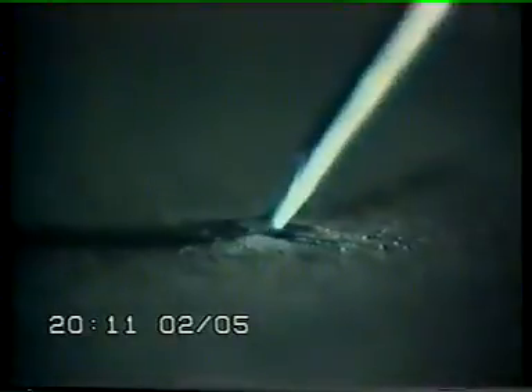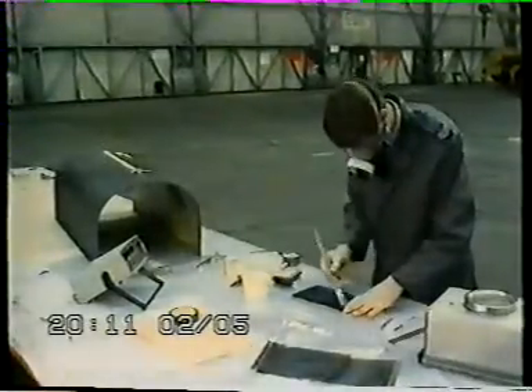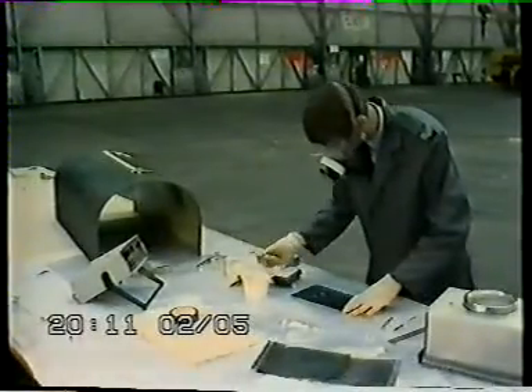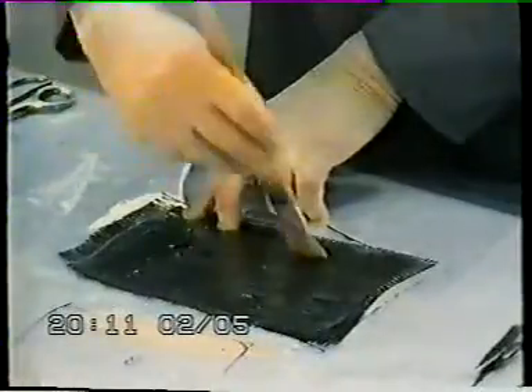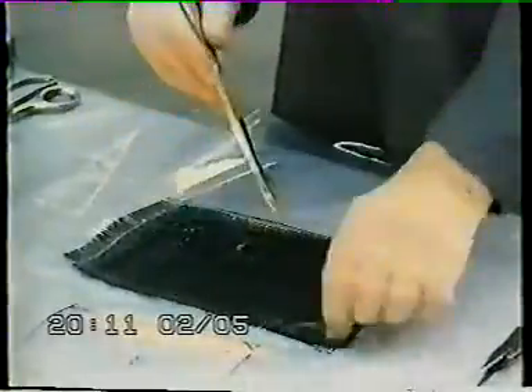For composite materials, neither corrosion nor fatigue should be a problem, but they do present other snags. Small impacts, dropping a spanner like this, for example, can cause delamination. In this case, it's just visible. On other occasions, the damage may be internal, with no trace of it on the surface. Repair must be carried out to the highest standards, and special techniques and equipment may be required.